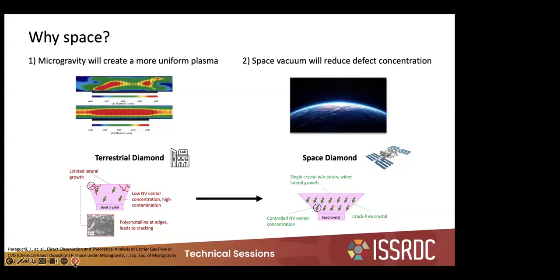So bringing all that together with the other IP and know-how that single crystal diamond brings to the table, we want to go from the old paradigm of limited lateral growth, low nitrogen vacancy center concentration, high contamination, and polycrystallinity at the edges, which can lead to cracking of the diamond, to a new regime where our space diamond will have single crystals without strain, wider lateral growth, controlled nitrogen vacancy concentration, and crack-free crystals. We believe that the type of crystal we'll be able to make in space will be superior to what is possible to be made on the ground.